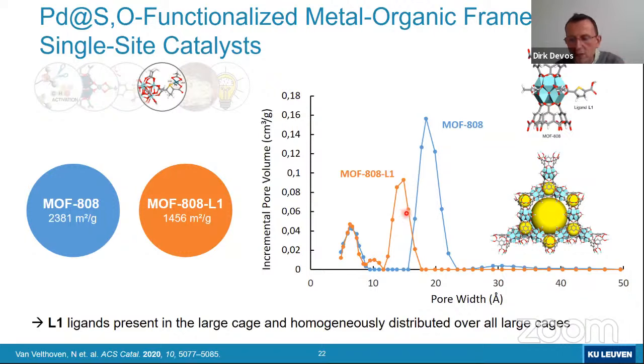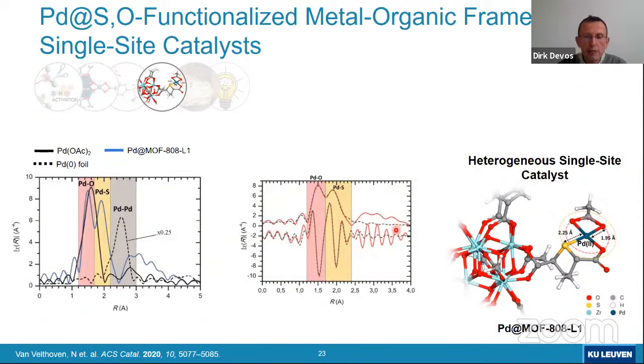We did also many other characterizations, like for instance solid state NMR, and that also proves that this ligand is in a very homogeneous fashion distributed all over the lattice of this MOF-808 material. We also looked at the palladium siting itself, again with XAS. And of course, that's a very nice case to look at with XAS because you have all these different binding atoms, the sulfur and the oxygen, and that gives you a very clear fingerprint. So we can indeed prove from these XAS data that the palladium is coordinating both to the carboxylic acid, but also to the thioether of the tetrahydrothiophene ring in the ligand.